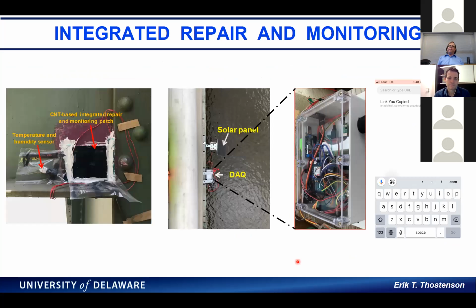Yep. And I think that combined with the high aspect ratio. So this was the motivation, that you have this small diameter reinforcement that's very high stiffness and strength. And I think also, if you look at an Ashby chart of carbon fibers, and in fact, in one of my papers, I created one of these charts, for carbon fibers, there's always a trade-off between Young's modulus and strength. So the higher strength fibers such as IM7 or AS4 have typically intermediate moduli.